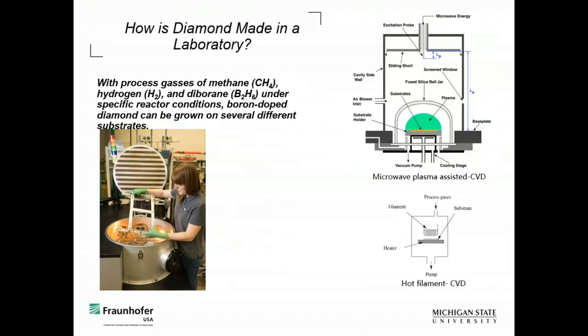I think I'll go through this relatively quickly, but essentially if we take methane gas, hydrogen gas, and diborane under specific reactor conditions, here's a microwave CVD reactor, we add microwave power and we create a plasma where we ionize these process gases, and then we will get diamond growth. So this is one way, via microwave assisted CVD. The growth rates are quicker in microwave CVD. However, the substrates can only be up to 6 inches in diameter. So this is excellent for some of our microfabricated sensors and things like that.